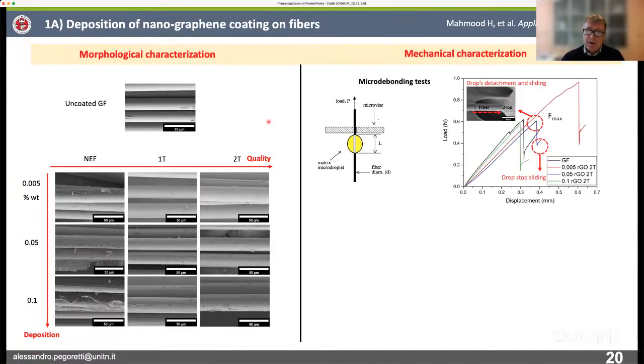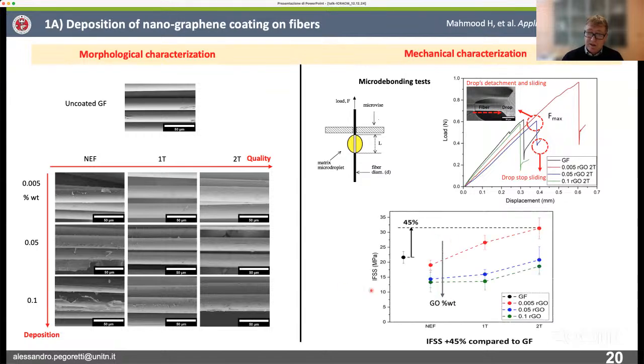In particular, we measured the micro debonding by using a very simple test that I already introduced before. By measuring the maximum load, which can be normalized to the contact area between the drop and the fiber, it is possible to obtain an interfacial shear strength. This interfacial shear strength, IFSS, in megapascal, is plotted here as a function of the intensity of the rubbing between the glass fibers and the Teflon rollers, and also as a function of different concentrations of graphene oxide, reduced graphene oxide, sorry, on the surface of the fibers.